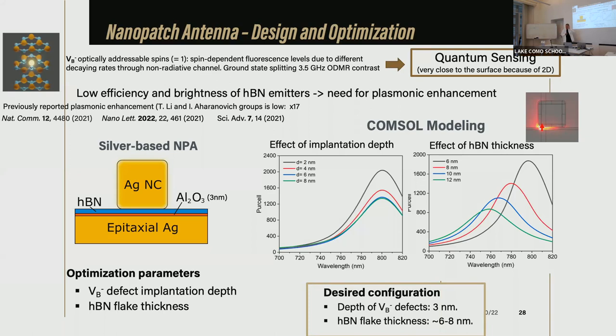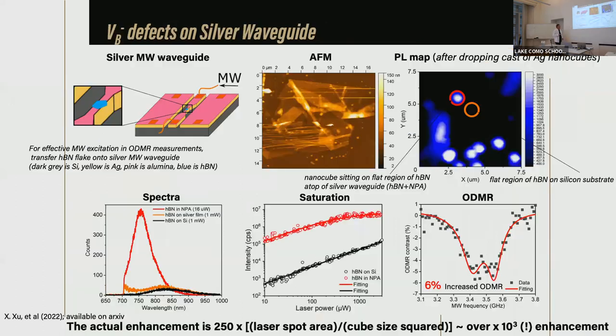It's not a single layer, it's a flake, around 6 nanometers, and the depth of defect, not surprisingly, somewhere in the middle. So in what we obtain, when we place this flake on a silver waveguide, we need the waveguide because we need to induce this spin degree of freedom with microwave. And the waveguide just enables this efficient excitation of the spin degree.